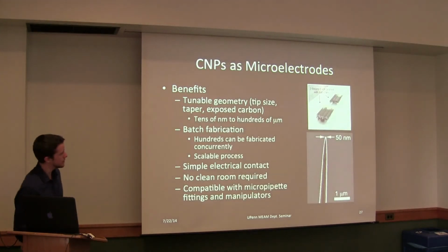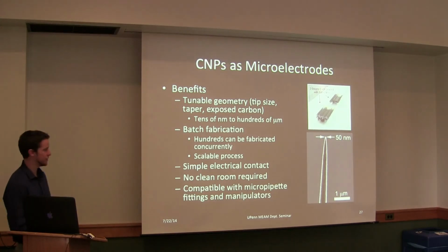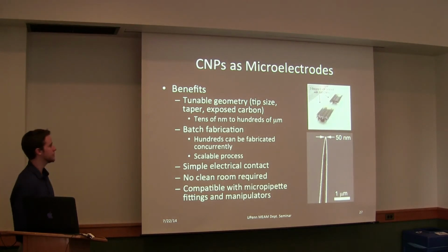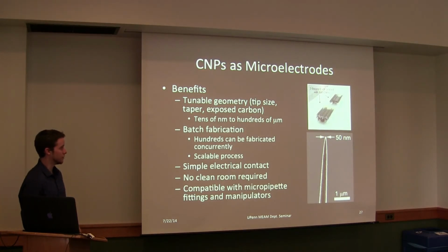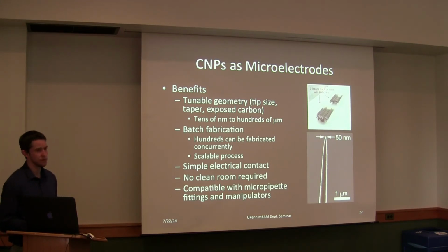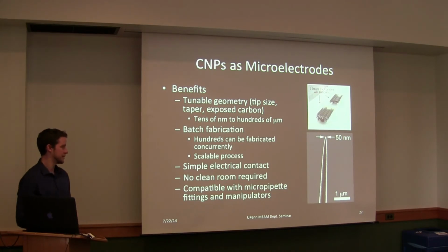The benefits of CNPs as microelectrodes, as I briefly discussed earlier, is that we have very tunable geometry. So the tip size, taper, and amount of exposed carbon are tunable. And we can range from tip sizes in the tens of nanometer range all the way up to exposed lengths on the order of hundreds of microns. So we have a very wide range. We have batch fabrication. So instead of producing these one by hand, we can fabricate hundreds concurrently. And it's a very scalable process. So this could be scaled up quite easily.